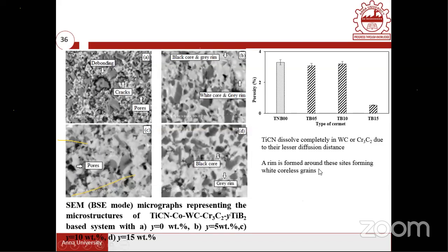Okay, a rim is formed around these sites, forming white coreless grains. So white core, gray rim. Sometimes you can have black core, gray rim. Here white core, gray rim. And the white core, gray rim is formed because of the precipitation mechanisms. Okay, precipitation dissolution mechanism. The gray rim is also a precipitation mechanism, and also along with the binder material it would be formed. And one can understand how much densification is possible with the nano TiB2 addition.